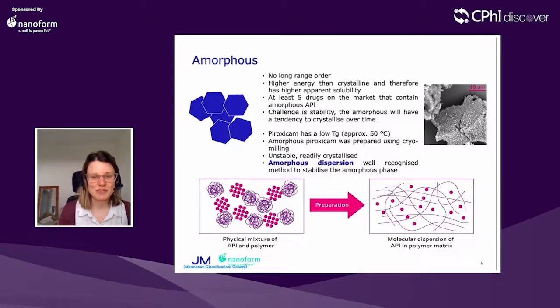On the SEM image I'm showing here, this was prepared after we'd generated the amorphous material by cryomilling, and we can see just in the preparation time of that material, we can see crystallites forming on the surface of those particles.